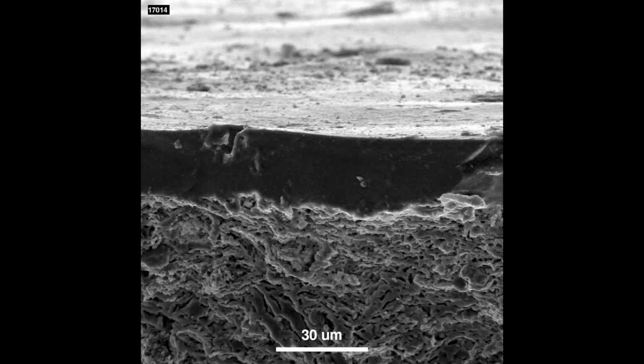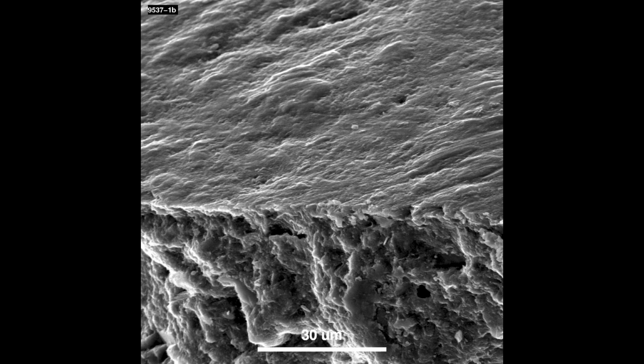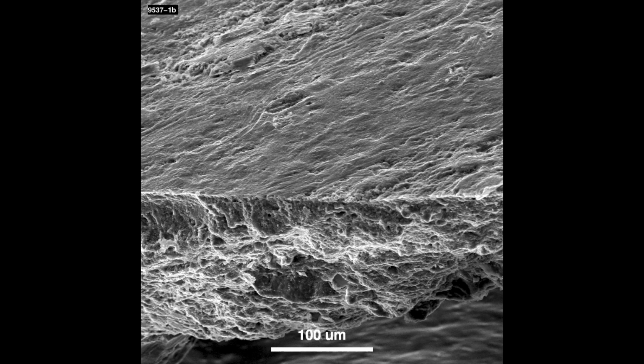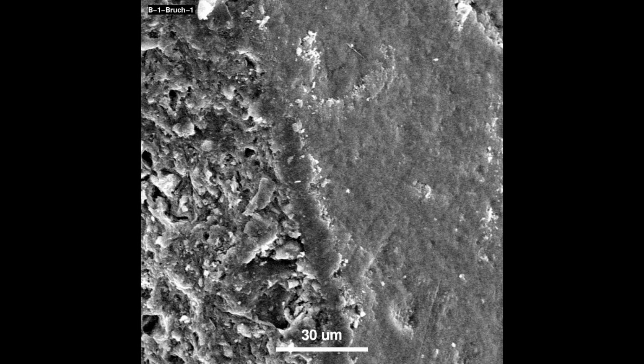What did the microscopes show? SEM. The SEM images were revealing the glossy layer was much denser, more compact than the pottery body underneath, which was more porous. Suggesting the slip was applied wet as a liquid. Exactly, as a suspension. It allowed it to form that smooth, dense layer, and the thickness was remarkably consistent, around 0.125 millimeters. Careful work. Very.